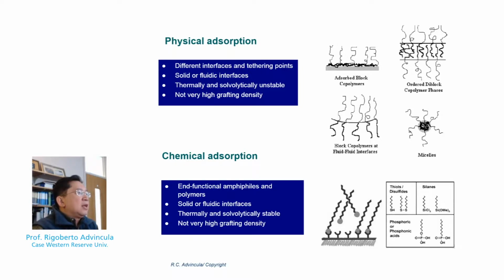One of the consequences here is that since they are not a chemical boundary or rely on the ordering at the interface with equilibrium, they do not easily achieve very high grafting densities. On the other hand, what we call chemical adsorption usually results in a covalent bond formation or tethering chemistry, which can be achieved by, let's say, silane chemistry or phosphonic or phosphoric acid chemistry on metals or oxides, or the interaction of thiol on gold. And this means that the adsorption can be achieved at a boundary, a surface, or an interface where this chemical adsorption or chemical interaction takes place.